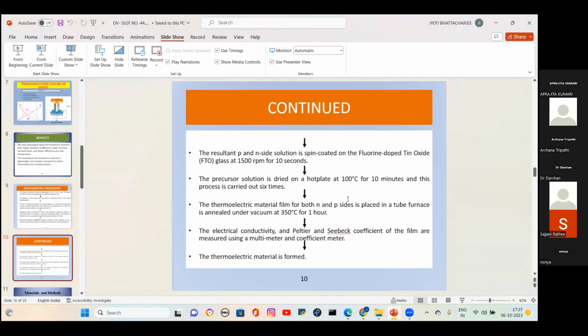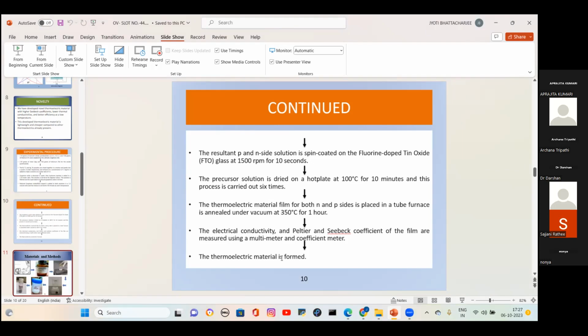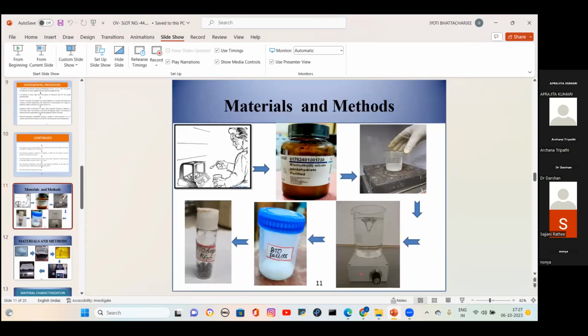The thermoelectric film that has been formed for both the N and P sides, I have placed in a tube furnace under vacuum at 350 degrees Celsius for 1 hour. Then I have done the characterization, and I found the Peltier and Seebeck coefficients using a Keithley electrometer and multimeter. And then my thermoelectric material is formed. These are the materials and the methods I have used.